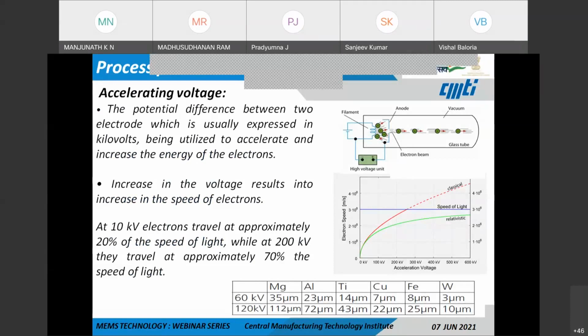The increase in the voltage results in the increase in the speed of these electrons. So when I see in this graph, at lower electron accelerating voltages, the speed of these electrons is slightly negligible, that is around 20% of the speed of light. The speed of light is 3 into 10 power 8 meters per second, and when the accelerating voltage is around 200 kilovolts, they travel at approximately 70% of the speed of light.